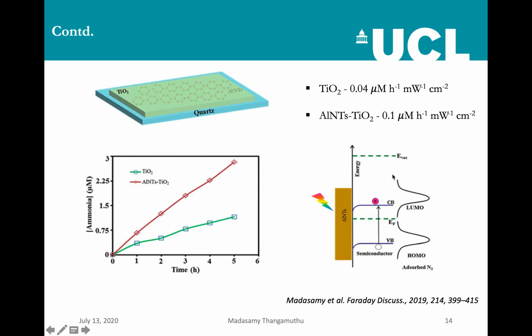So that's why we propose this schematic in my work: once we shine a light on aluminum nanotriangles, it can enhance the charge carrier generation from the TiO2 semiconductor, and that electron enters into the lowest unoccupied molecular orbital of the nitrogen molecule, and there it probably forms some intermediates, called some nitrogen radical or N2 minus, before it converts into ammonia. So the exact mechanism still has to be explored, but at the end we managed to produce some micromolar concentration of ammonia. That's the good news.